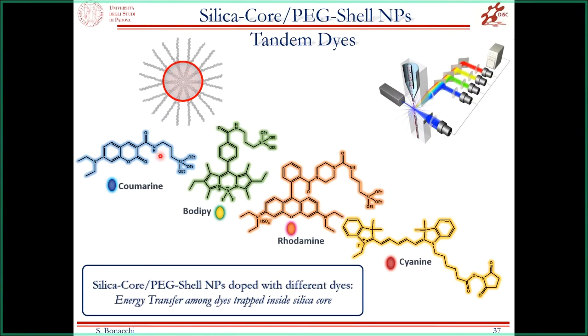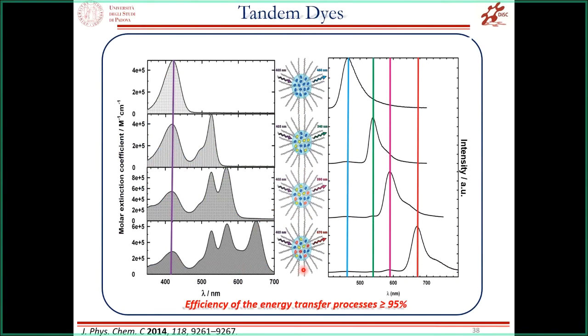In particular, we selected a sort of cascade of different kinds of dyes with different energy levels in order to optimize the energy transfer among them. So a coumarin, BODIPY, rhodamine, cyanine, all trapped inside the silica core in order to obtain energy transfer among dyes trapped inside the same structure. And as you can see here, as a final result, we can tune the absorption spectrum of this silica nanoparticle, and we can tune the emission properties of this doped silica nanoparticle just by playing with the different dyes that we trap inside.